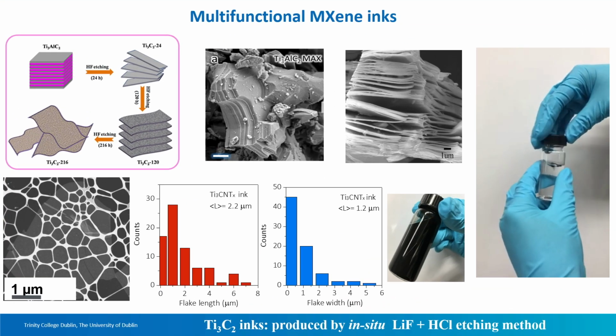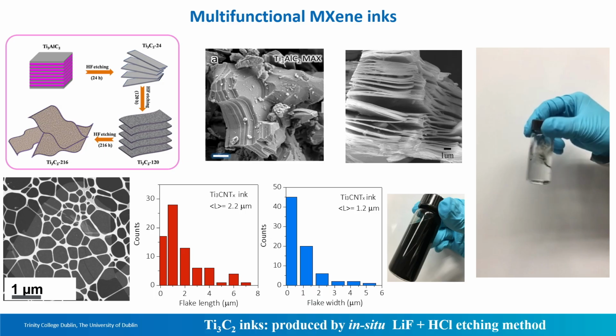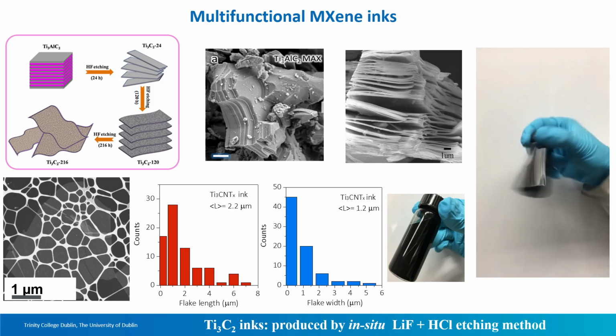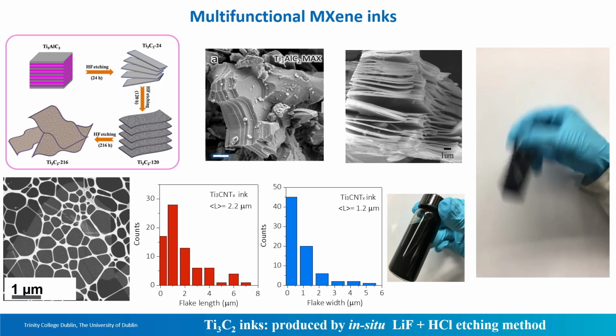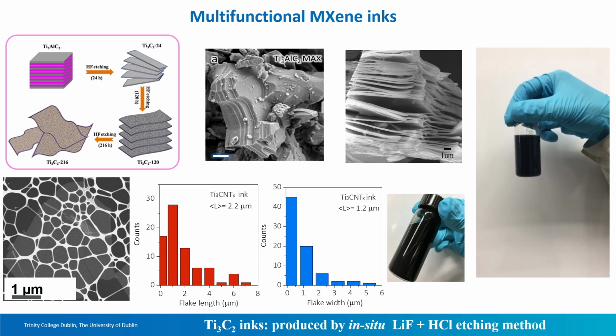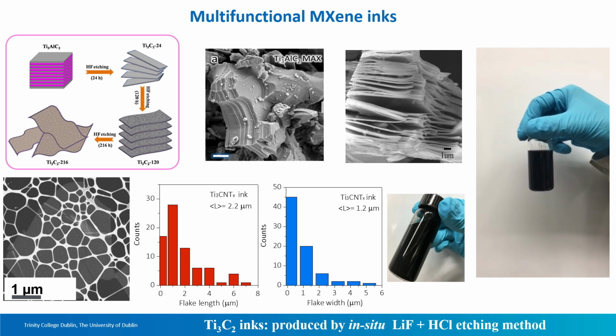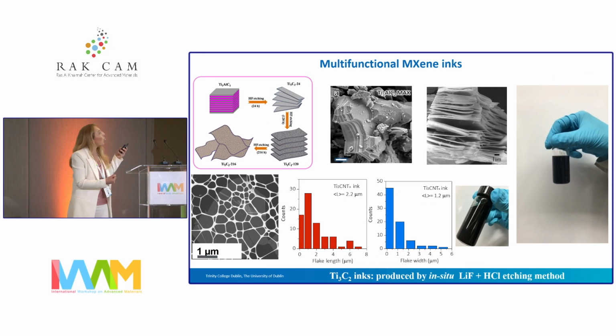In addition to that, in the last decade, we've started to work with a fairly different class of 2D materials. They come from MAX phases, ceramic materials based on transition metal carbides and carbonitrides. In this case, these layered crystals are quite special because what holds the crystals together, the interlayer spacing, is made of very strong covalent bonds. So we use either HF etching or other acidic etching, where we effectively etch away the middle layer in this ceramic material, aluminum in this case, and what we get are these accordion-type structures.